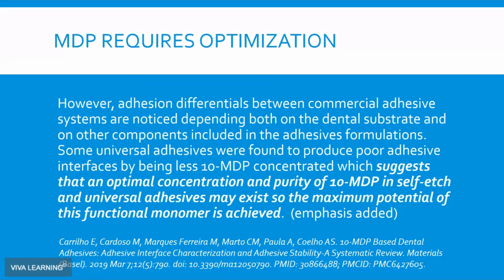In Carrilho et al.'s paper, which was another systematic review regarding the characteristics of MDP-containing adhesives and cements, it was very fascinating because they mentioned in a key paragraph one statement that jumped out at me: "However, adhesion differentials between commercial adhesive systems are noticed depending both on the dental substrate and other components included in the adhesive formulations." So it's not just MDP. It's the ratios and the mixtures of other factors. He continues: "Some universal adhesives were found to produce poor adhesive interfaces by being less 10-MDP concentrated, which suggests that an optimal concentration and purity of 10-MDP in self-etch and universal adhesives may exist, so the maximum potential of this functional monomer is achieved." And of course, I added that emphasis. Now, what does that mean? That means that MDP in and of itself requires some playing with the ratios.